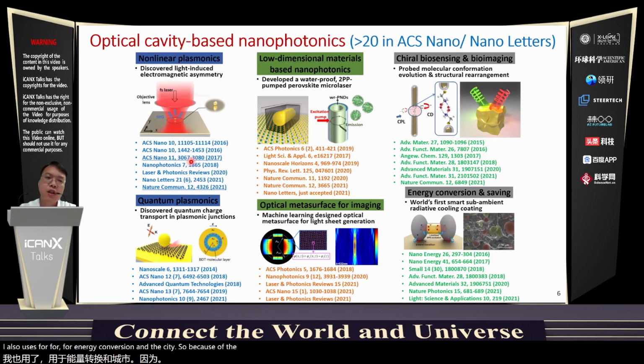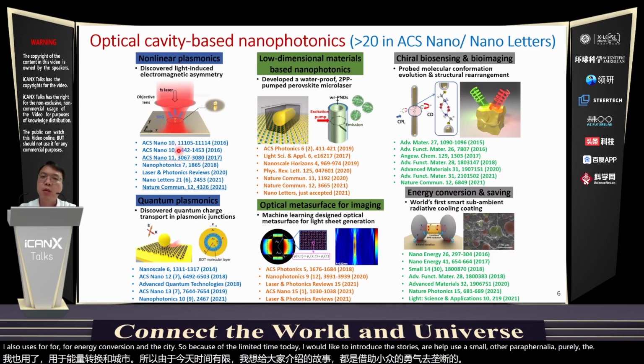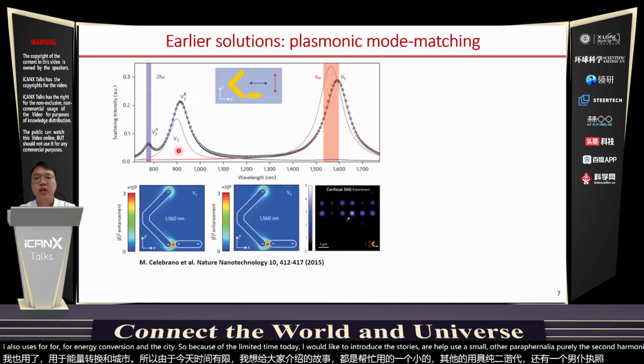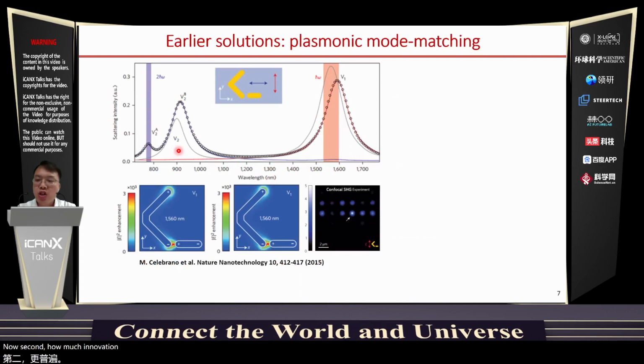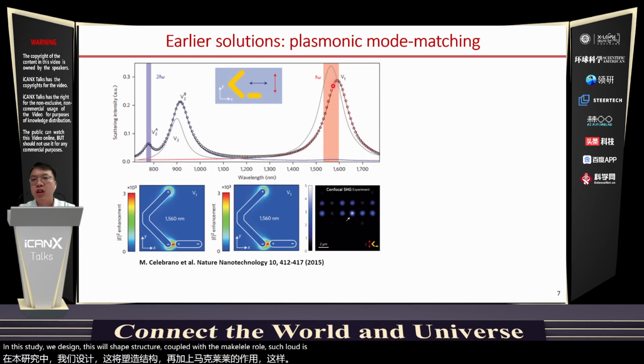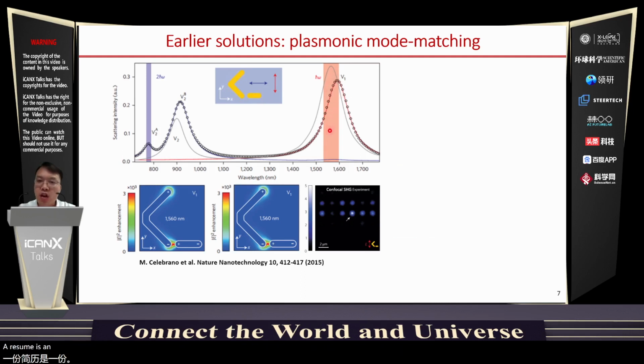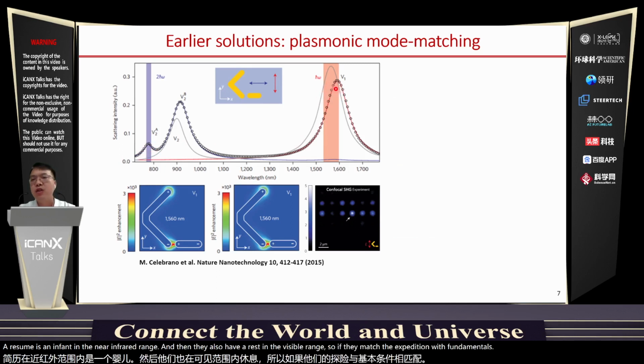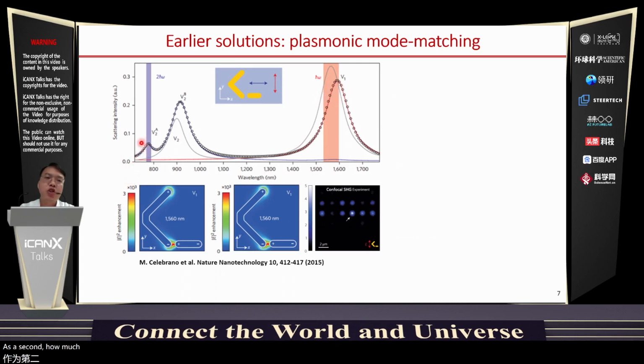Because of the limited time today, I would like to introduce two stories on how to use plasmonic nanocavities to manipulate the second harmonic generation and photoluminescence in those interesting structures. Now, second harmonic generation in metallic structures has been studied for a long time. The general solution to enhance the second harmonic generation is based on mode matching. For example, in this study, they designed this V-shaped structure coupled with the metal nanorod such that it has a fundamental wavelength resonance in the near infrared range, and then also a resonance in the visible range. So if they match the fundamental excitation wavelength with the longer wavelength resonance and the second harmonic generation with the short wavelength resonance, they can enhance the second harmonic generation, as seen from their measurements.